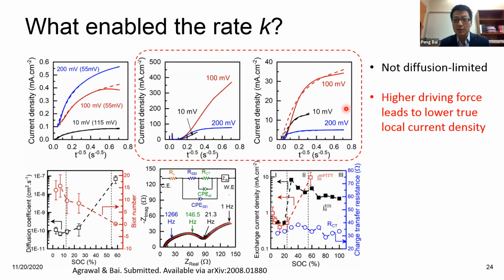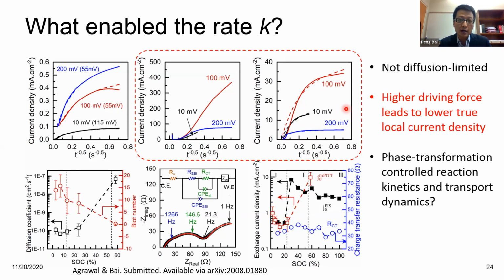It's actually not hard to be understood because there are two effects of the increase of the driving force. Here, it simply activated more particles. So the total current is distributed to more particles, yielding a much lower true local current density. That's why our conclusion is that the process is really not diffusion controlled or limited, nor reaction controlled. It's really just phase transformation controlled because it affects two levels of processes.